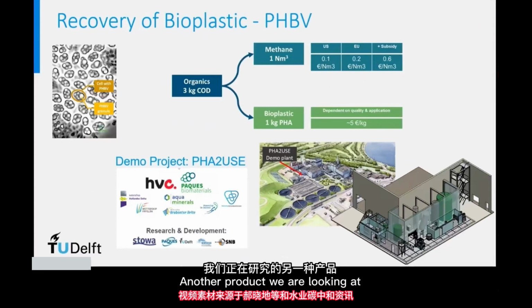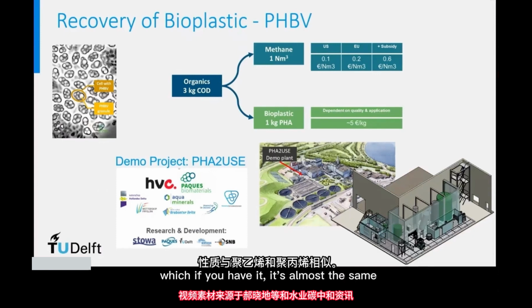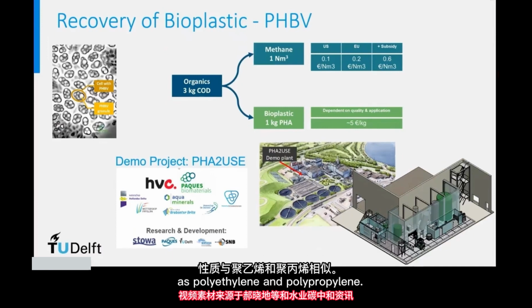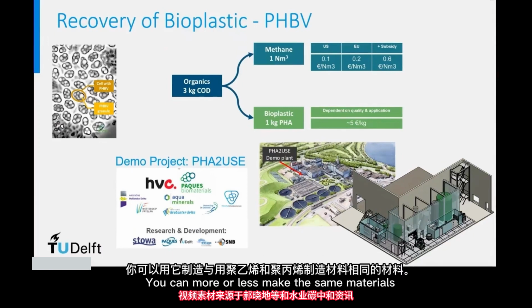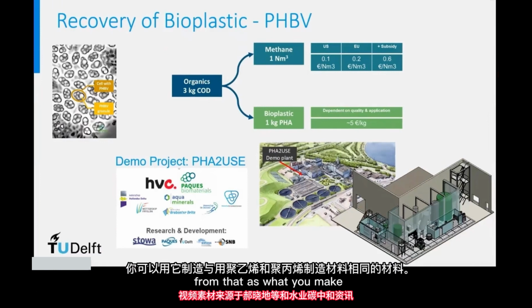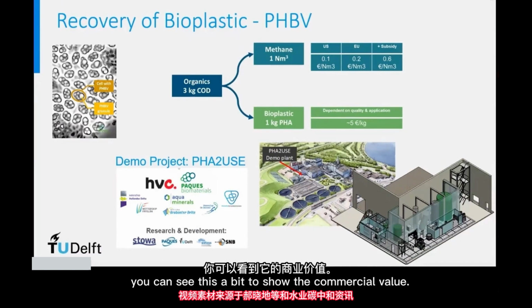Another product we're looking at is producing PHA from wastewater. Now, PHA, polyhydroxyalkanoate, is a compound which is almost the same as polyethylene and polypropylene. You can more or less make the same materials from that as what you make from polyethylene and polypropylene. And here you can see, this is a bit to show the commercial value.